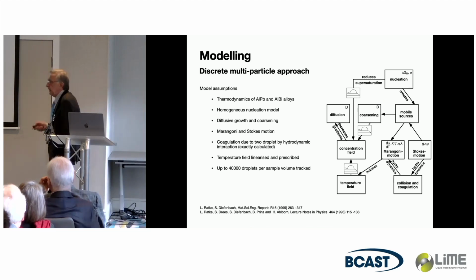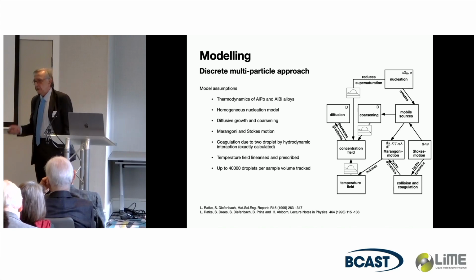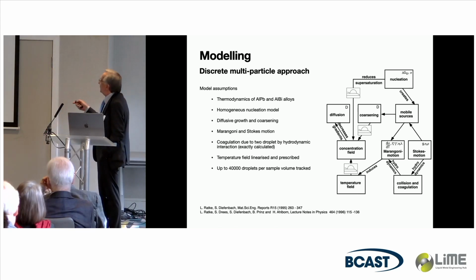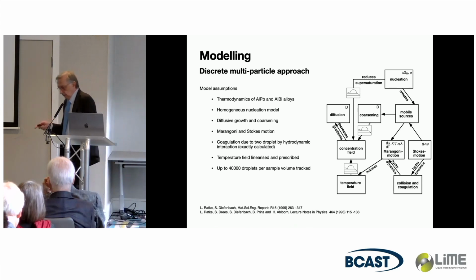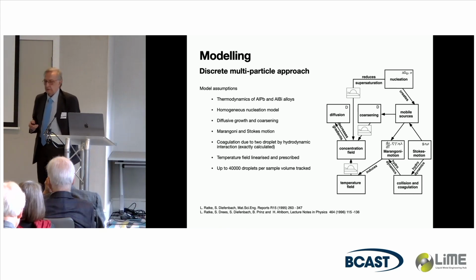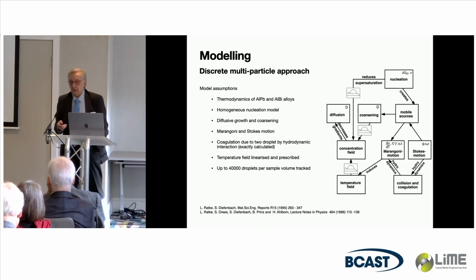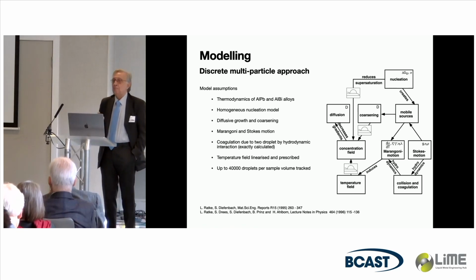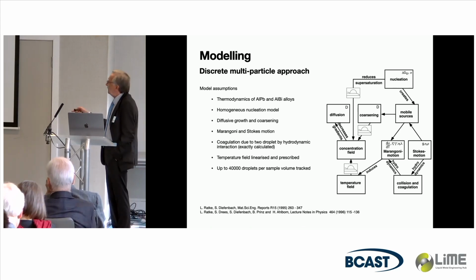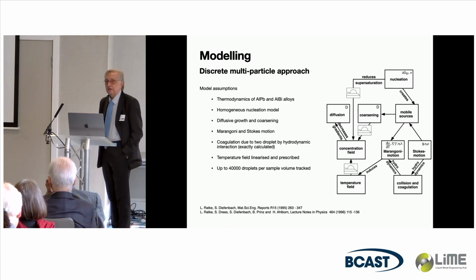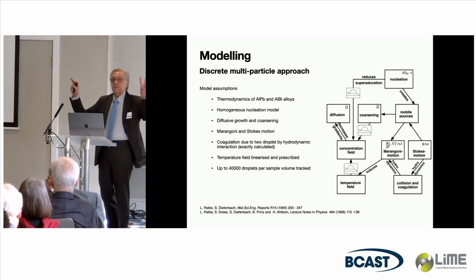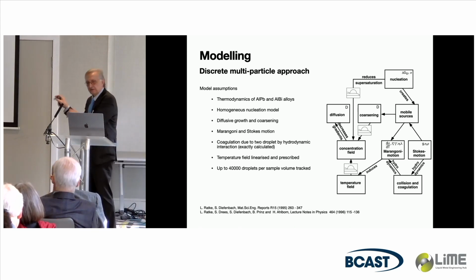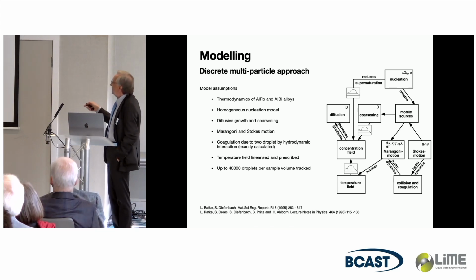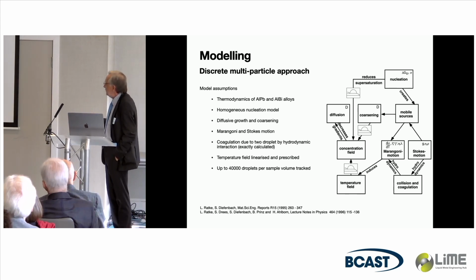What you think about then modeling is everything depends on everything. Because you have a lot of processes, how to do that? We said first, for this alloy, at that time in a bigger project, the group of Bruno Predel and Ferdinand Sommer in Stuttgart really measured all the thermodynamic quantities of aluminum lead and aluminum bismuth. This was very important. So we had the full thermodynamics with optimized phase diagrams. And assuming it's homogeneous nucleation, at that time we thought it is that, then you can, of course, say, well, you have a cooling, you have a prescribed temperature field, you have a nucleation event.